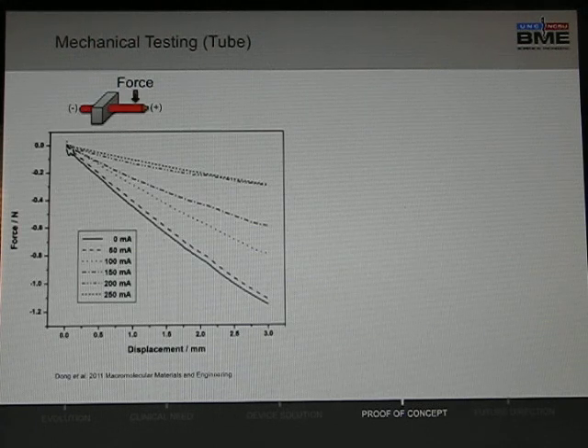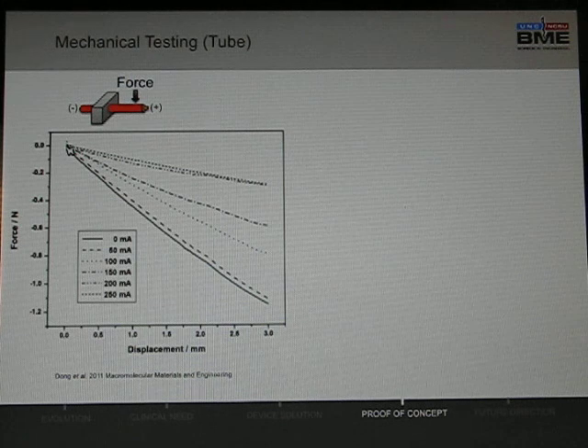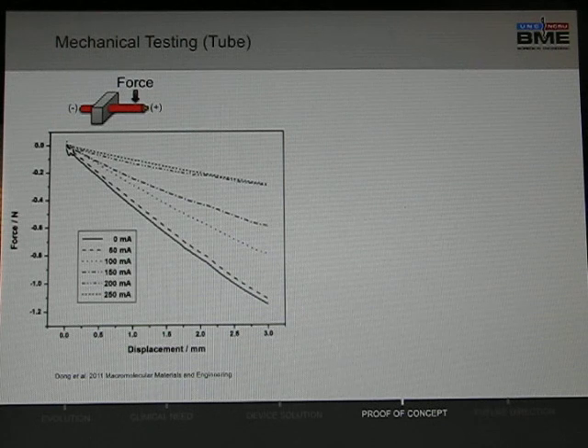So we powered on the tube and did cantilever bending tests. Here we plotted force over displacement of 3 millimeters. As plotted, you can see the force decrease with increasing currents applied, and a very little difference from 200 and 250 milliamps.